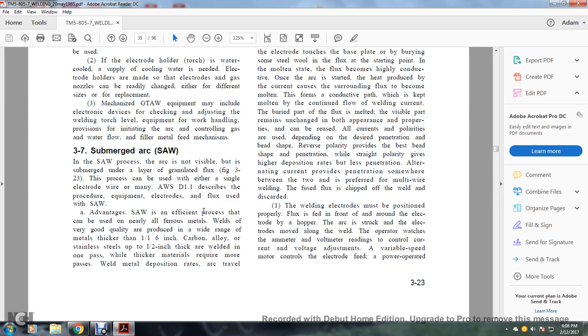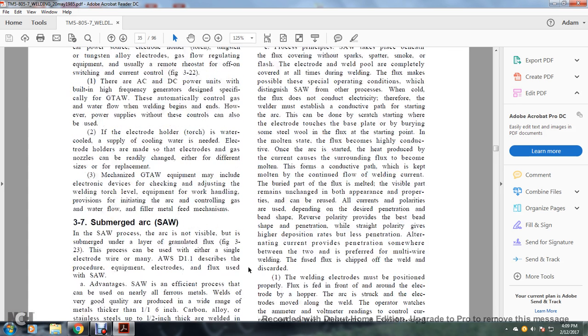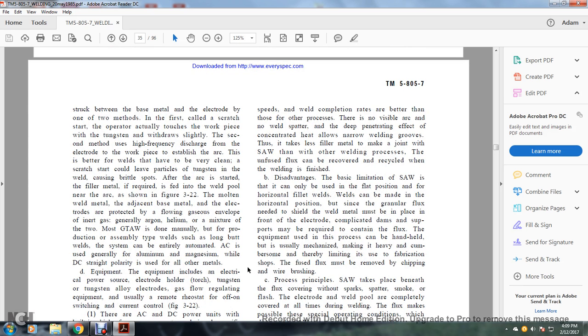Advantages: submerged arc welding is an efficient process that can be used on nearly all ferrous metals, welded with very good quality. It produces a wide range of metal thickness, thicker than 1/16 of an inch. Carbon, alloy, or stainless steel with 1/2 inch thickness can be welded in one pass, while thicker materials require more passes. Weld metal deposition and arc travel speeds, and weld completion rates, are better than those of other processes. There is no visible arc when the weld is being done.